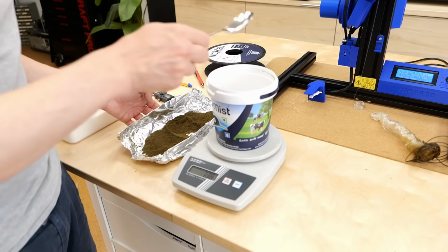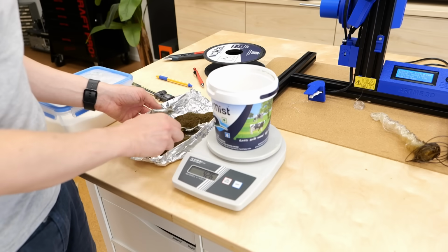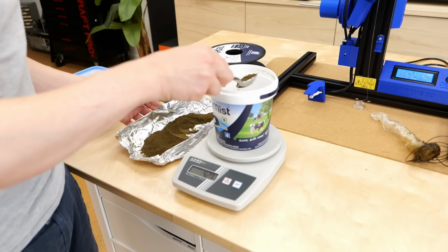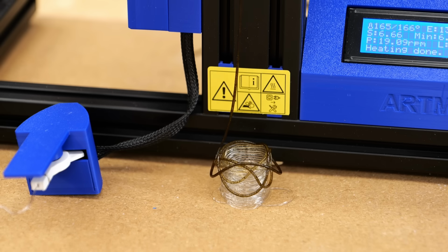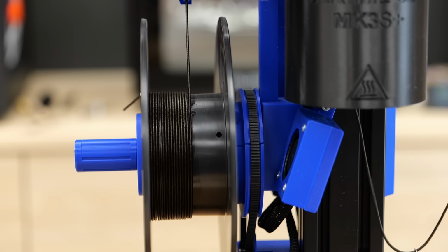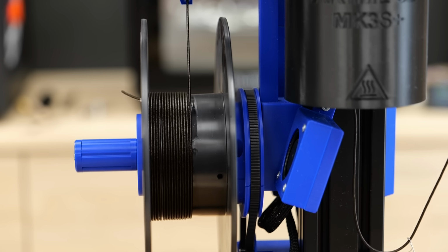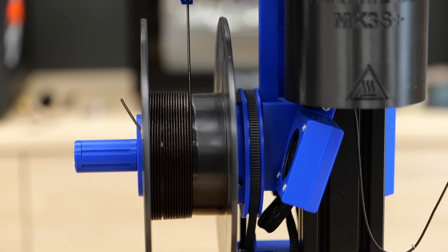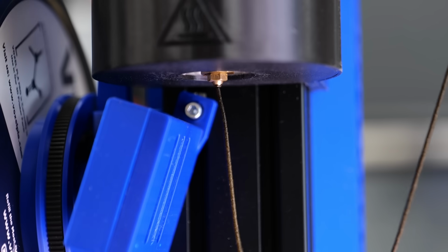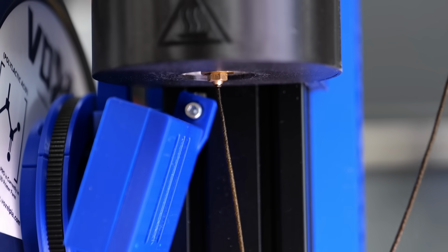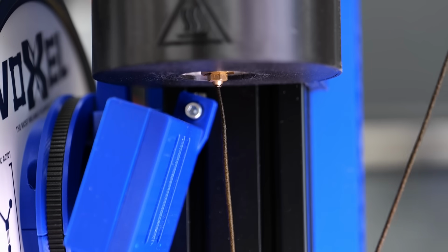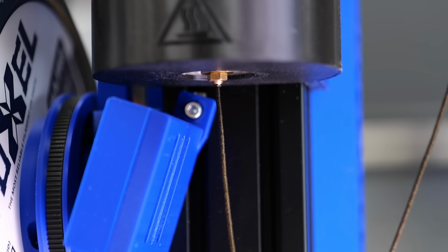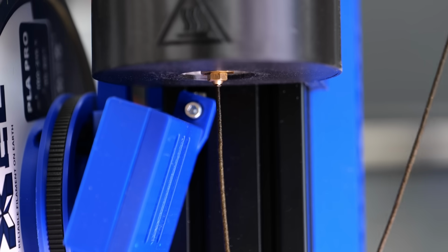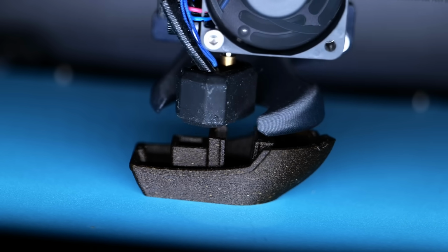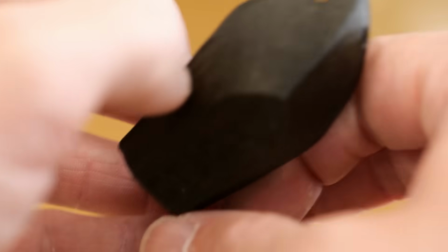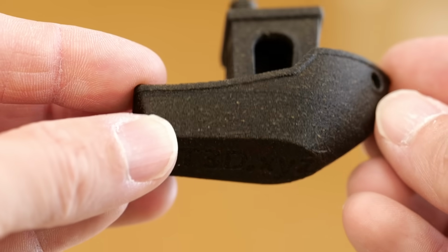After this reassuring success, I made another batch and this time added 10% cow dung by weight into the material, and even this extruded surprisingly well. Spooling it wasn't a problem, even on the normal small diameter of an empty spool. The only problem I again encountered was that after half or 2/3 of the material went through the extruder, the filament started foaming again, ruining the rest that was still left over. Yet I had plenty for a 3D Benchy, which again looked amazing when printed on a regular 0.4mm nozzle.